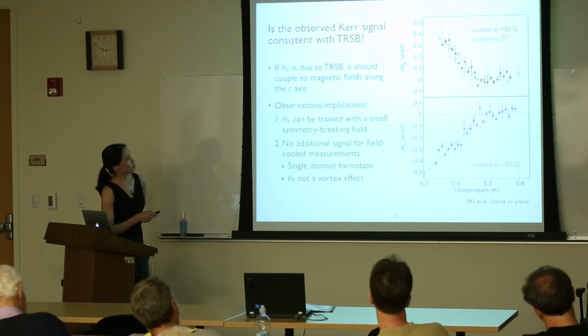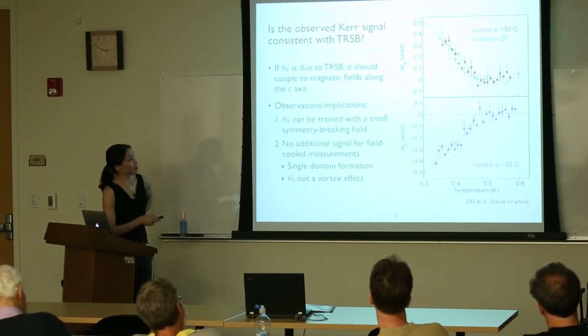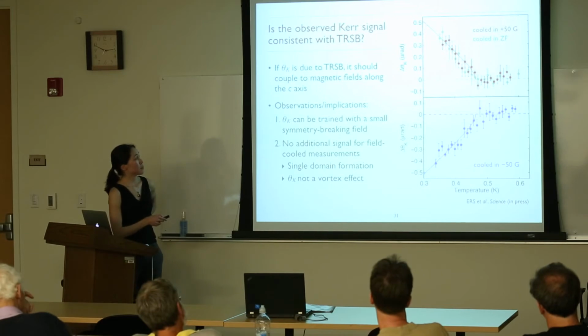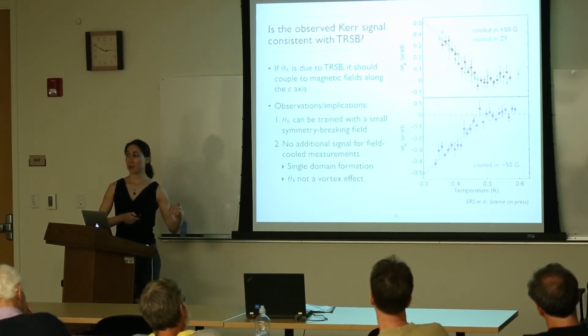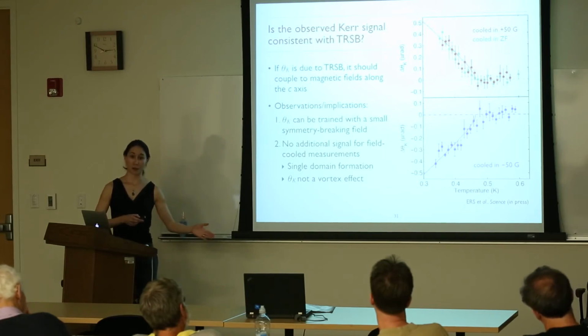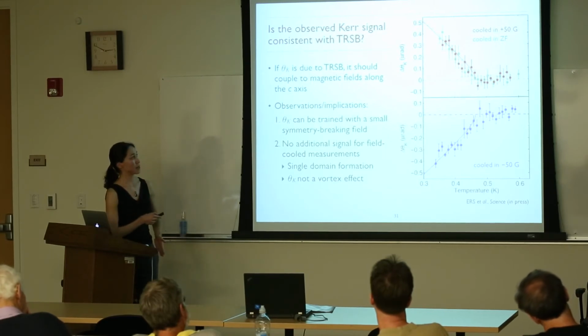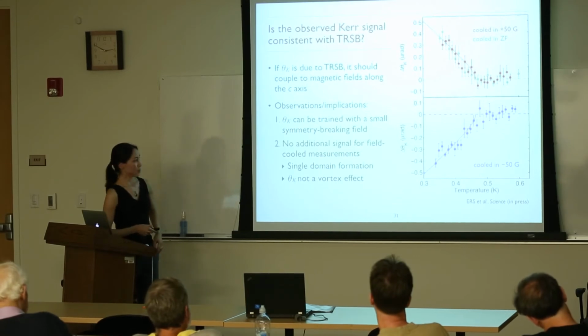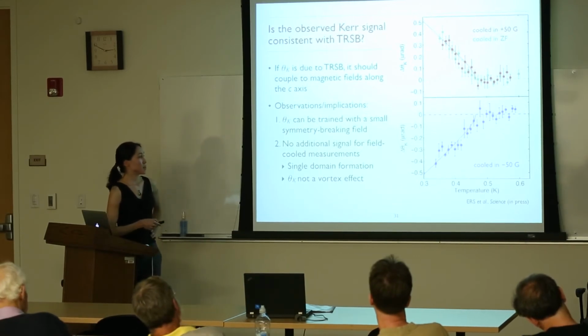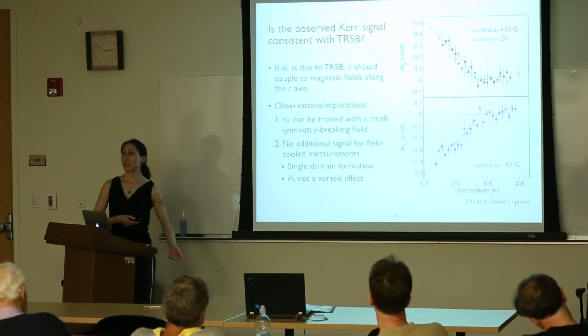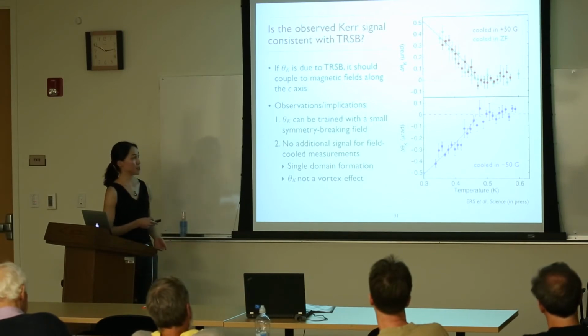The zero field data from the previous slide is plotted here in gray. And the red data is what happens if I do the same experiment, except I've cooled the sample down in a small positive field, turn the field off at base temperature, and this is what I get when I measure upon warm-up. And then the blue is if I do the same thing, but I cool in a small negative field and look at what's left over as I warm up in zero field.